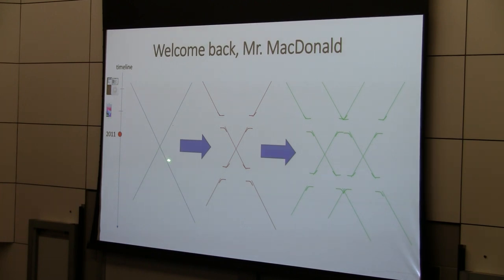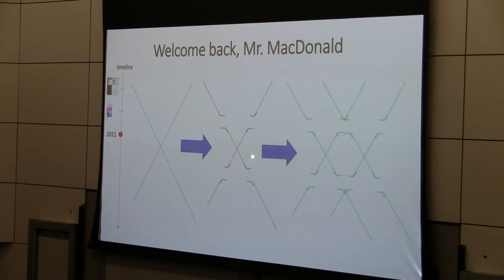And Allan MacDonald realized the following. If I take graphene, and then I convert it to twisted bilayer graphene. Here is the band structure of twisted bilayer graphene of one of the two layers. So what I have here is the original Dirac dispersion of graphene. And because of the Moiré pattern, I now have created a copy of this dispersion, but with a much smaller energy scale. What Allan MacDonald realized is that what one has to carefully take into account is the fact that an electron in one layer and the electron in the other layer can actually hop between the layers, so they can hybridize with each other.